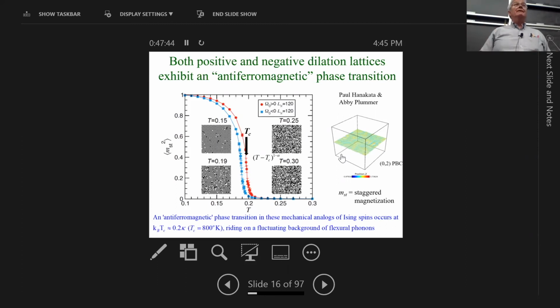So we can escape again, because there's long wavelength stuff not only going on with the flexural phonons, but also going on with the diverging correlation length of an Ising antiferromagnet. So this is a system which has two things that are simultaneously critical. The flexural phonons are automatically critical all the time in the flat phase, and then we have this Ising stuff on top. You can see it, but it doesn't seem to be very big, but it's allowed in the simulations for sure, absolutely.